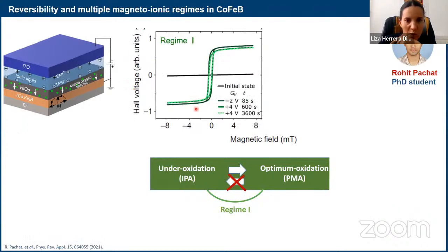Here we did it in regime 1. You can see we go from the initial state to something that is more perpendicular, not even the full perpendicular state. And then we applied 4 volts, which is pretty much the limit of what the ionic liquid can do. Even for very long times, there's hardly any reversibility. So that was not very nice. So we said, well, this is probably, again, the hafnium oxide interface, we should maybe be using another oxide.